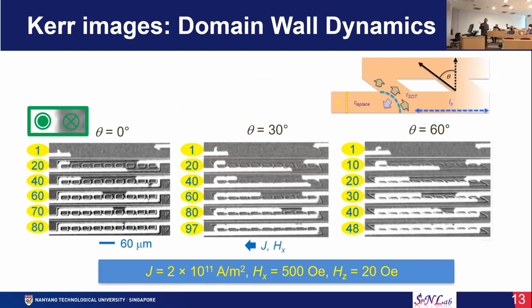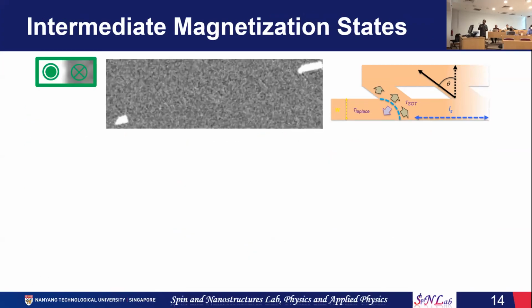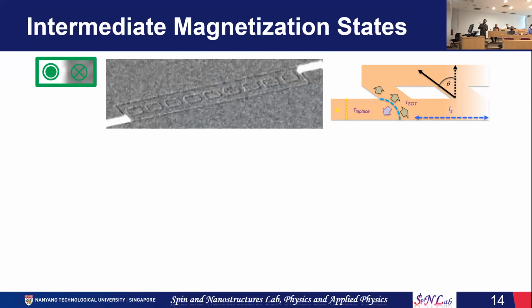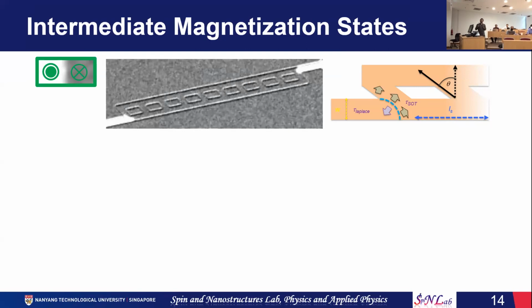Okay. So now we need to probe the domain wall dynamics in the MOKE, Kerr microscopy setup, and we see that for theta equal to 0°, it takes 80 pulses to completely sweep, and for theta equal to 30°, it takes much larger pulses. For 60°, the number of pulses required is again small. So it also shows that for theta equal to 30°, maximum pinning strength is observed. And if you see this video, we get how intermediate magnetization states are observed also in experiment as well.